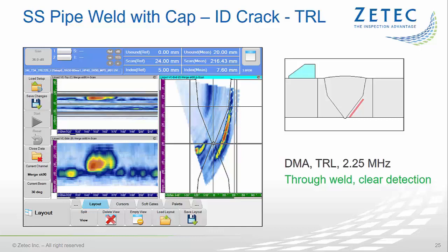So if an austenitic weld configuration with single-side access needs to be inspected, L-waves drastically improve the quality of the examination. We do have to be aware, though, that through-wall sizing for far side flaws is often very challenging due to weak and not well resolved tip signals.